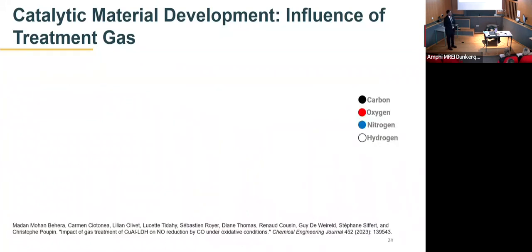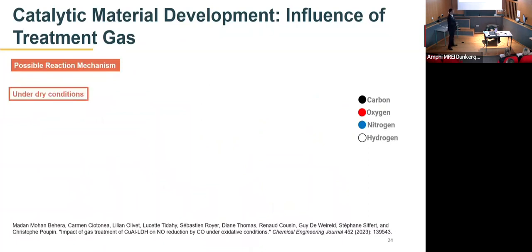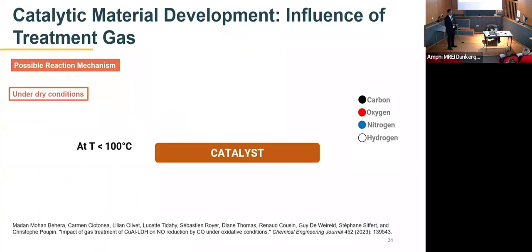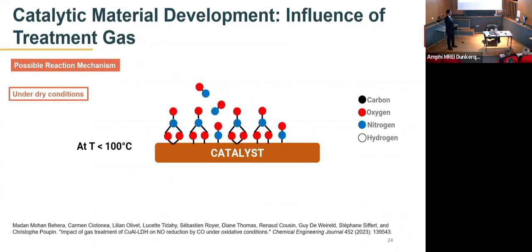So based on the different literature studies for the reaction mechanism, we propose a reaction mechanism that could happen in our reaction system. So in this case, under the dry reaction condition at a temperature of less than 100 degrees Celsius, the nitrogen monoxide from the gas stream can adsorb on the surface of the catalyst to form different nitrate species. However, there could be some adsorption of the carbon monoxide on the surface of the catalyst, forming either adsorbed CO species or carbonate species on the catalytic surface.